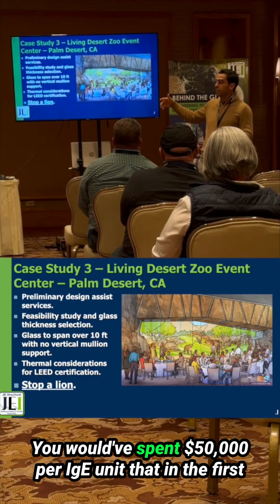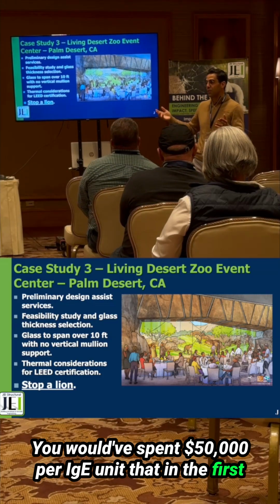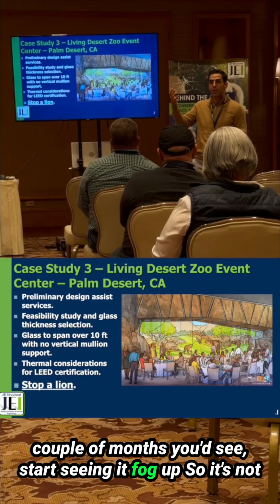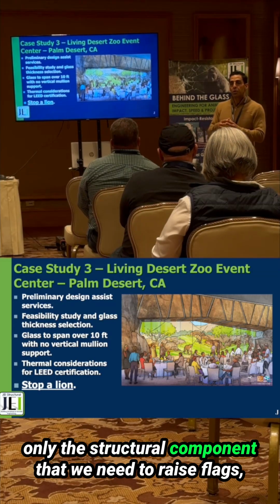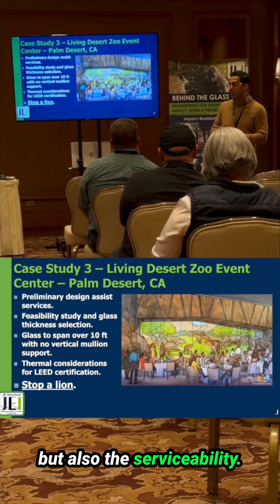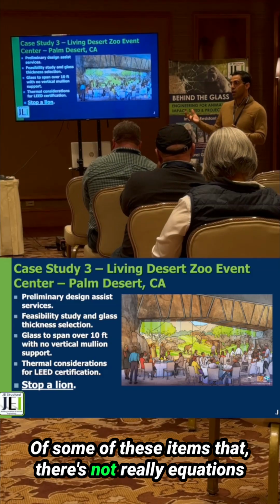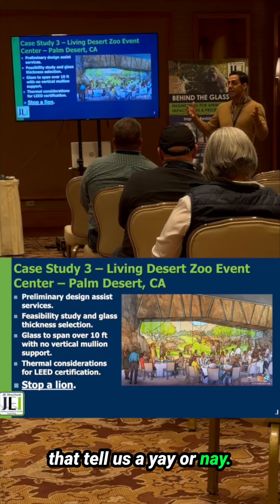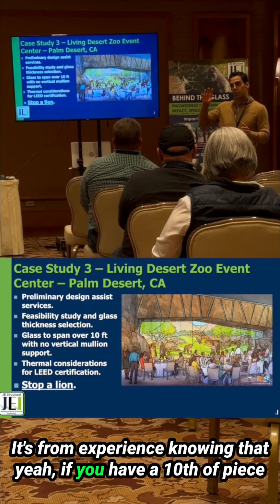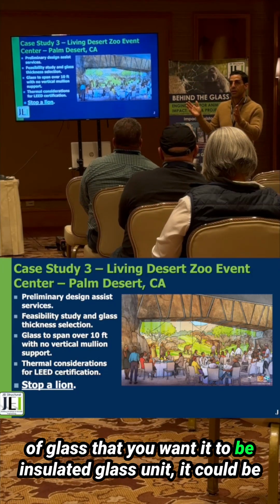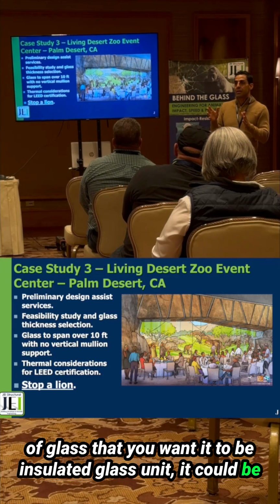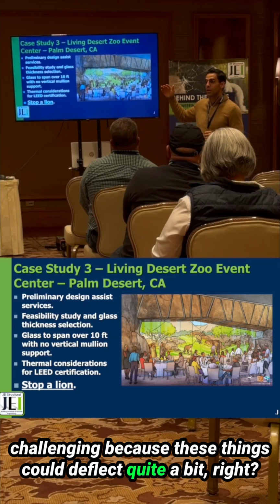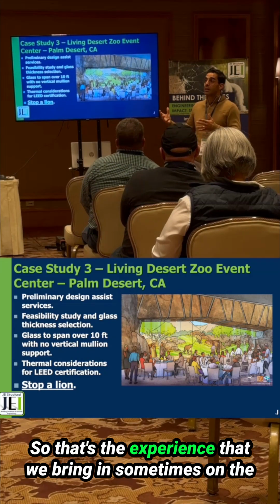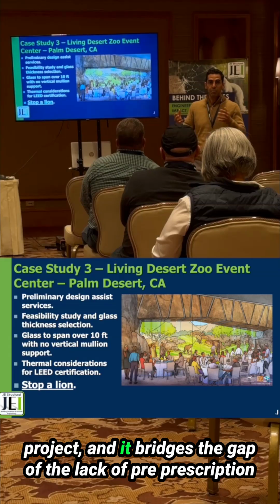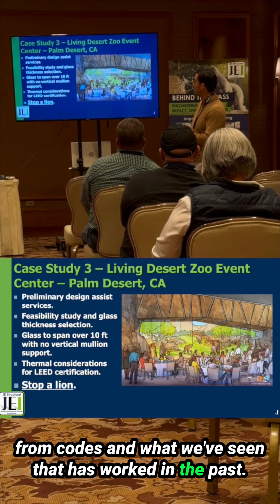You would have spent $50,000 per IGU unit that in the first couple of months you'd start seeing it fog up. So it's not only the structural component that we need to raise flags, but also the serviceability of some of these items that there's not really equations that tell us a yay or nay. It's from experience knowing that, yeah, if you have a 10-foot piece of glass that you want it to be insulated glass unit, it could be challenging because these things could deflect quite a bit, right? So that's the experience that we bring in sometimes on the project, and it bridges the gap of the lack of prescription from codes and what we've seen that has worked in the past.